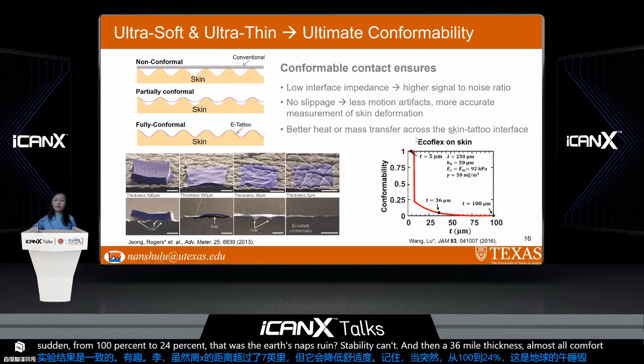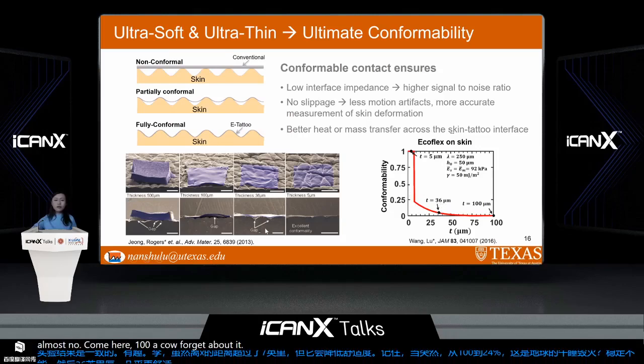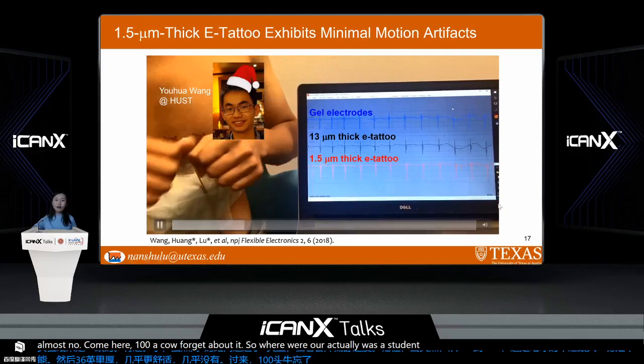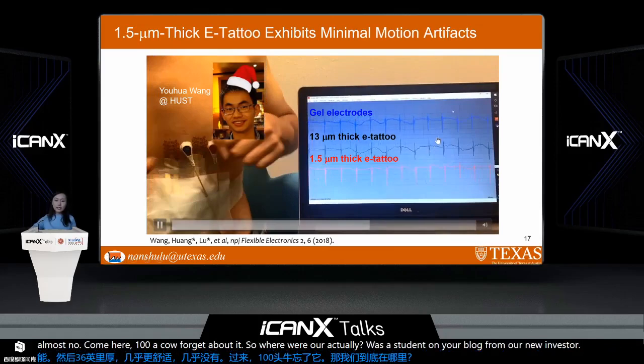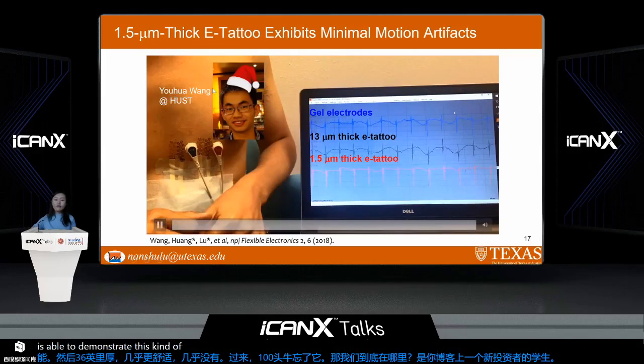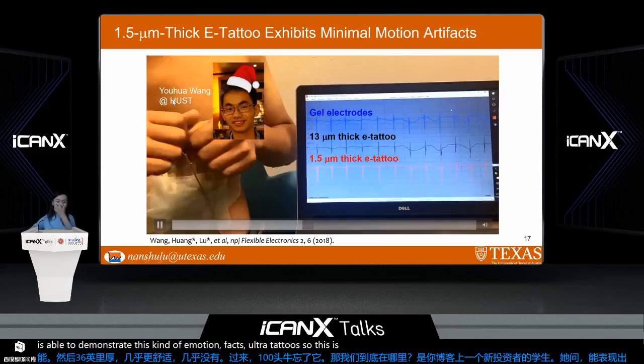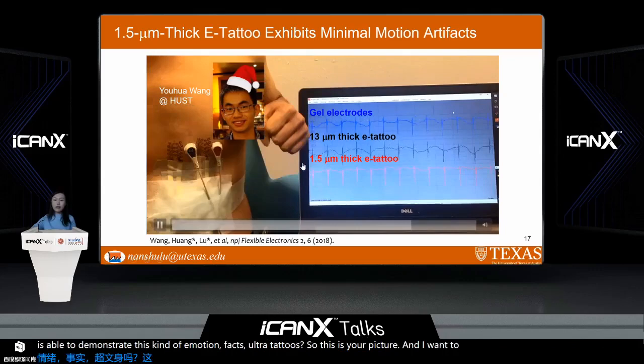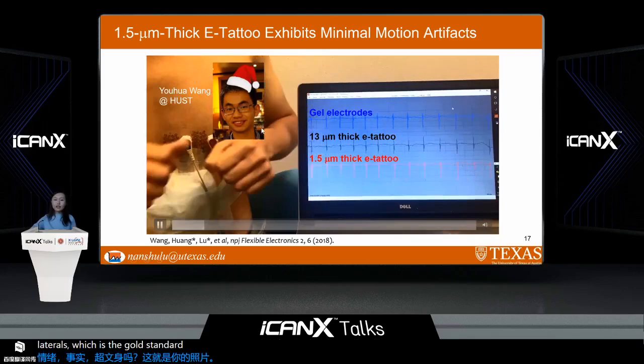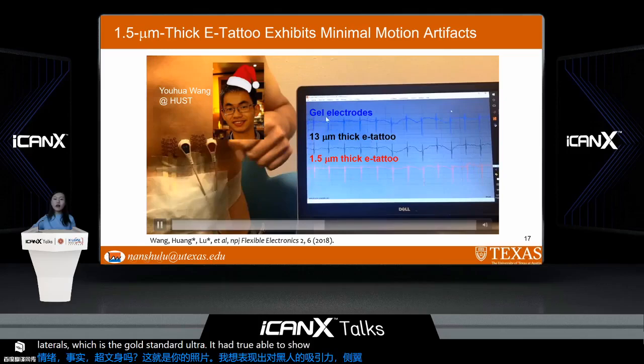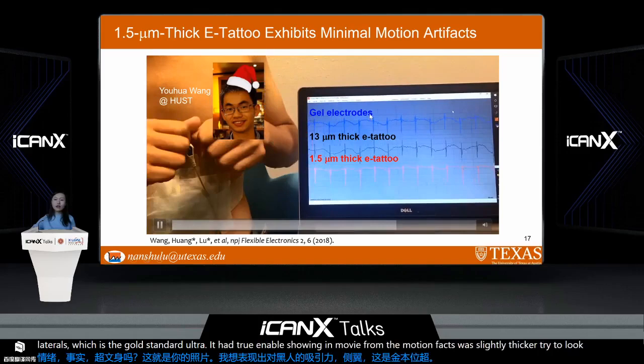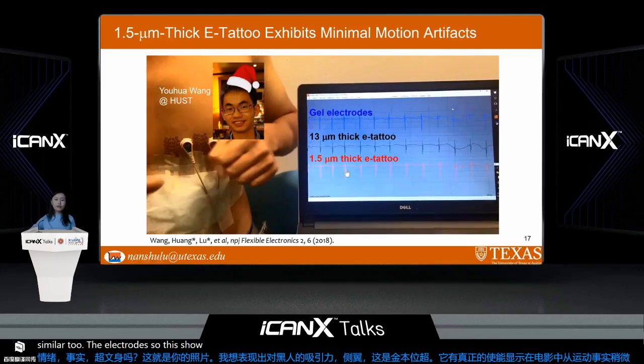Therefore, a visiting student, Youhua Wang from Huazhong University, HUST, is able to demonstrate this kind of limited motion artifacts in ultra-thin e-tattoos. This is Youhua's picture. And we are able to show, even comparing with wet gel electrodes, which is the gold standard, the ultra-thin e-tattoo is able to show immunity from the motion artifacts. The slightly thicker dry e-tattoo has motion artifacts similar to the gel electrodes. So this shows the importance of the thinness and softness of the e-tattoos.